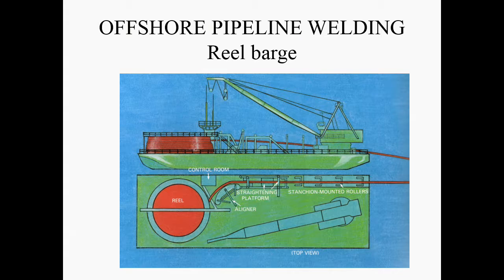One problem with this is obviously that in order to roll this pipe onto the spool, you need a huge area on land where this is done. The other limitation is because there are two techniques. You take the vessel close to the shore, and from the shore the pipe is pulled directly onto the vessel, or the entire reel is taken out by a very large crane. It's deposited on the land, and after spooling, the crane will take it back onto the vessel. So the limitation is the power of that crane. Will it be able to actually lift it and put it on the vessel?